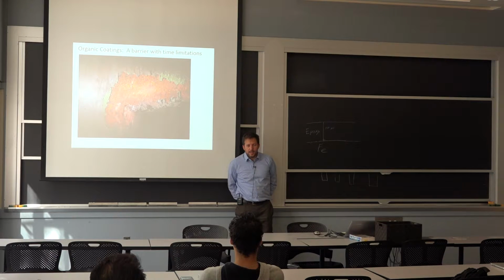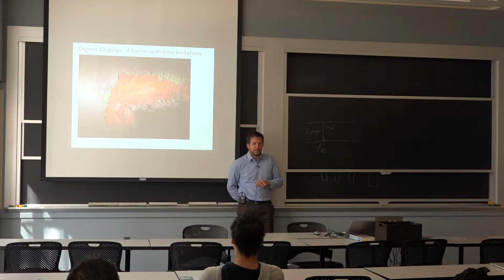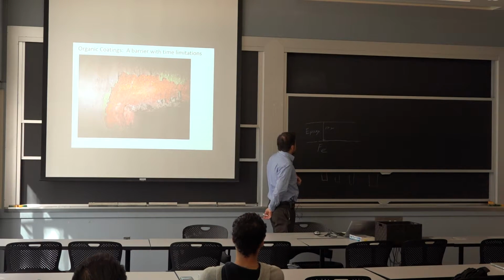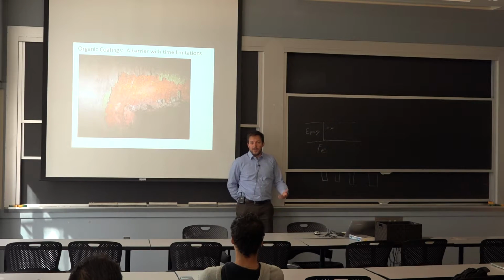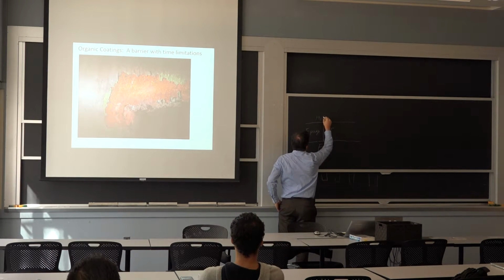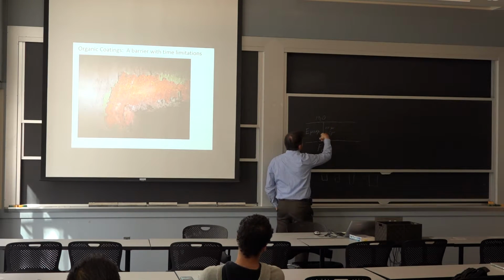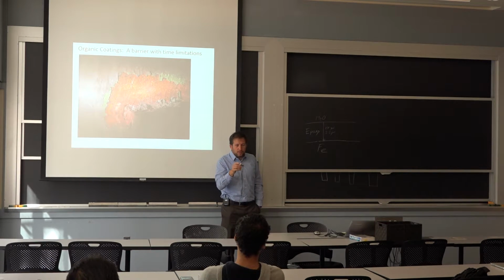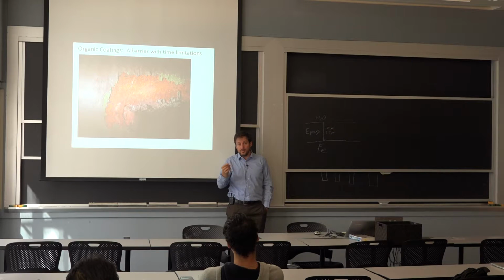So I think that it makes you think a little bit about why it's never a permanent solution. The physics works against you. Eventually, it will get there. It's a matter of how thick your epoxy is or any other organic coating you use. If it's just a latex paint, then it's just a year or two, or less. It's just a matter of how fast all that moisture is going to get into the surface. And one very particular thing here is if you do have a notch, if you have one area that's unprotected, then it starts corroding from day one.